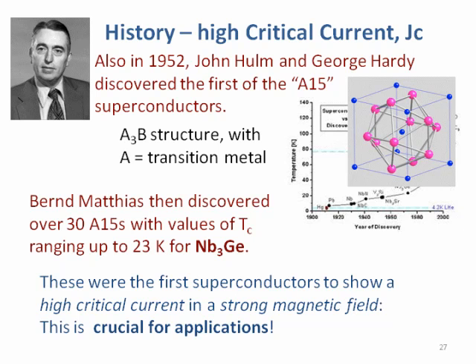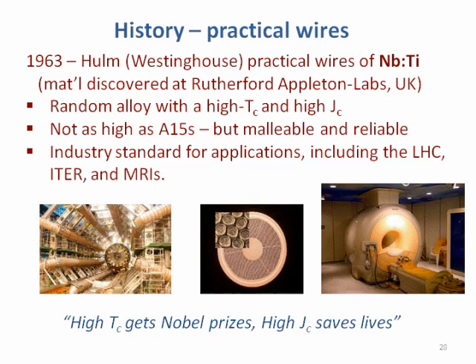This material, niobium titanium, is a random alloy. You just mix niobium and titanium and smear them up together, and you get a malleable material; you don't have to keep the crystal structure, and it's the most practical superconductor. So even though niobium germanium, the last one I showed you, has a higher Tc and a higher ability to carry current and field, this is the one that we use because it's more reliable.